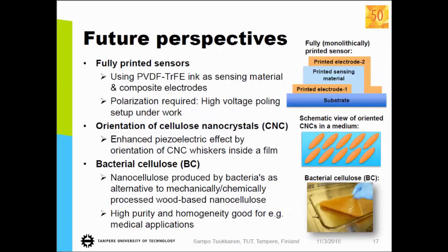So okay, what do we want to do in the future? Going towards the fully printed system is, of course, the aim. And then we have this kind of printable PVDF material, which is commercially available, PVDF-TrFE. First you have to print it, and then you have to polarize it to get the working sample. And about the nanocellulose, this is what we would like to have: the film and oriented nanowhiskers inside the film. But how to do this in practice, there are some challenges to realize it.